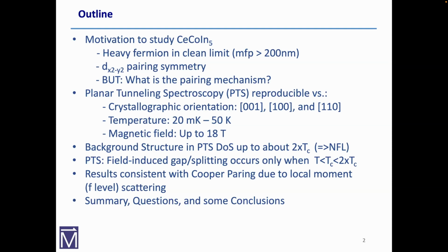When we go up to T star, we don't see much, which is an important clue. We do see this interesting field-induced gap. I'll show you the data; the data will speak for themselves. And I'll just point out that the results are consistent with f-electron scattering, Kondo scattering, probably having something to do with the pairing.